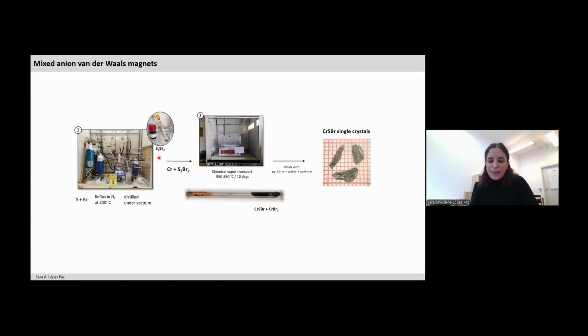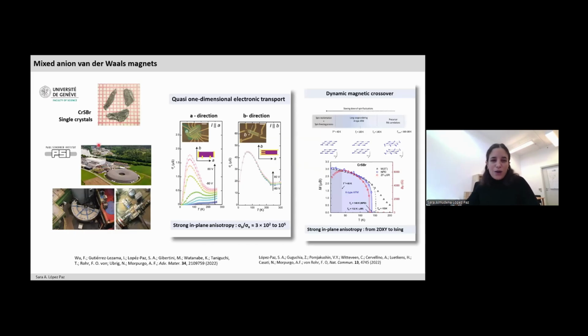With this, we will then perform a chemical vapor transport reaction, and we could isolate large single crystals of this van der Waals material. So once we had our crystals, we could actually go to PSI and use all possible techniques that we could find there. But we could also, in collaboration with groups in nanofabrication at the University of Geneva, test the actual performance of these materials in nano devices and see how this combination of chalcogen and halogen anions